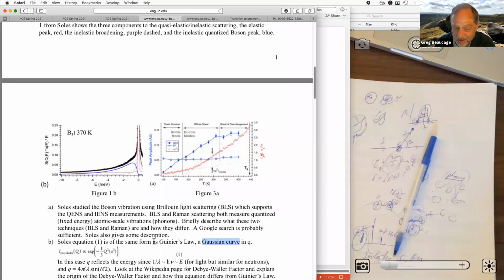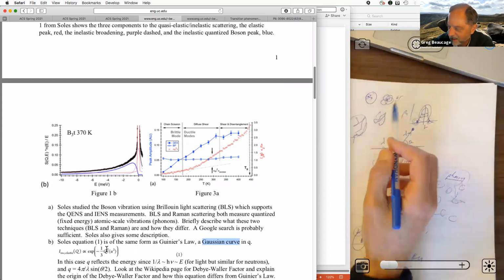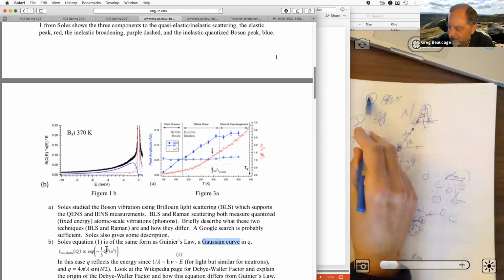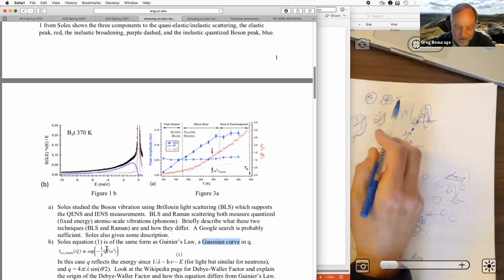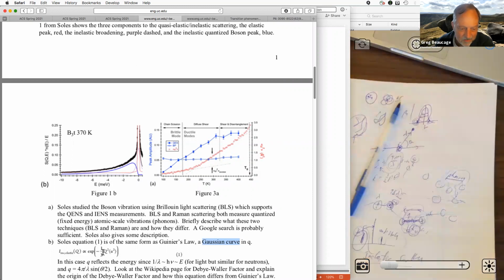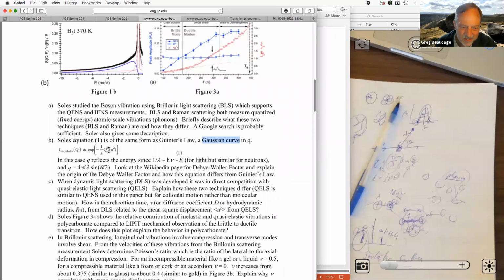So the link between the two is they're both talking about some kind of random thing, so you fall to a Gaussian or bell-shaped curve to describe it. The distinction between the two is what causes the bell-shaped curve. Here, thermal motion is causing it, and here, just the random isotropic choosing of where you start describes it. Now, it's exactly the same function. That's the kind of thing that should make you think about this, right? So it's exactly the same function. It's q squared Rg squared over 3, negative exponential. That's the same thing as Guinier's law.